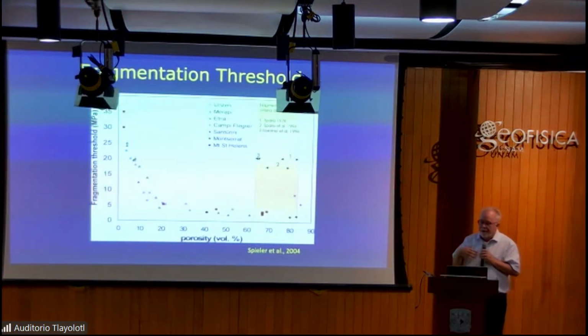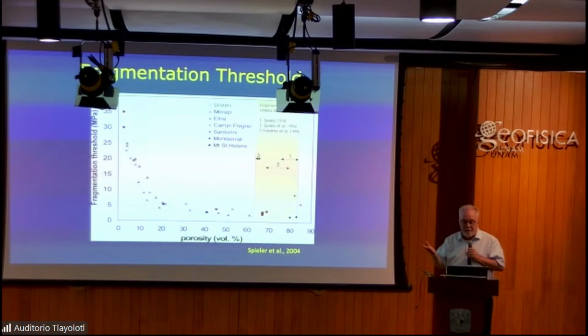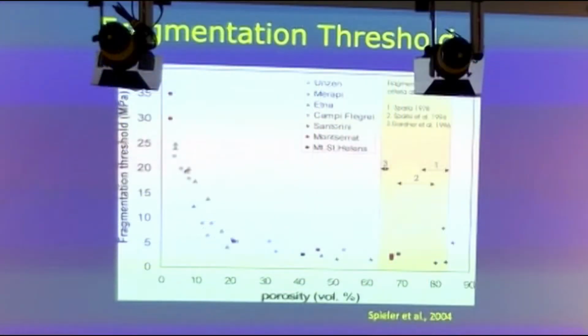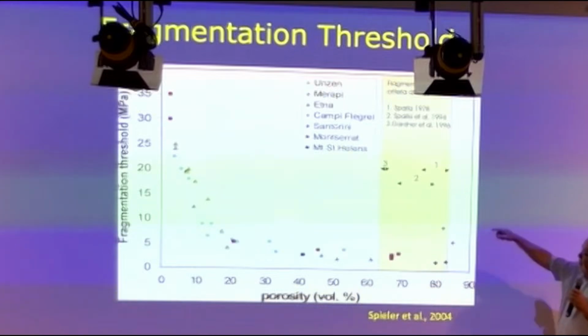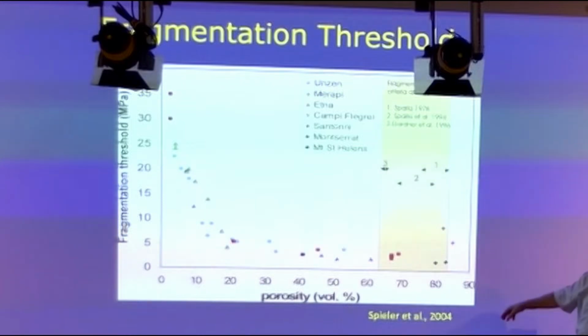And we can parameterize it. We have to come up with words to describe the different properties. This one is the threshold, which means the minimum delta P required to produce that ash, and it's a function of porosity. You have the whole world up there in terms of chemistry, yet they all lie on one line, more or less. And it just shows that it's physics here, not chemistry, which matters. And it's the porosity or the bubble content which gives the strength, tensile strength of the rock. Nobody is surprised to hear it when they hear it. And there's about a factor of 10 difference in the strength of a low porosity rock to a very high porosity one, in this case, glass-based.